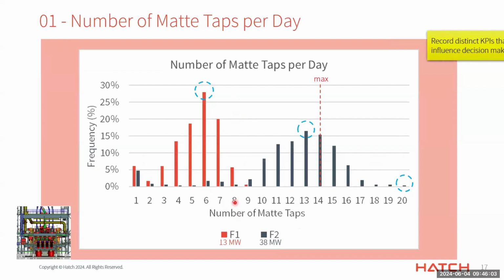So the average number of matte taps per day align well with the project design at 6 and 13 for furnace 1 and furnace 2 respectively, but the model then goes further to show the range of matte taps while considering process upsets and planned and unplanned downtimes, as seen with the lower taps, and when the furnace operates optimally, as seen with the higher taps per day.